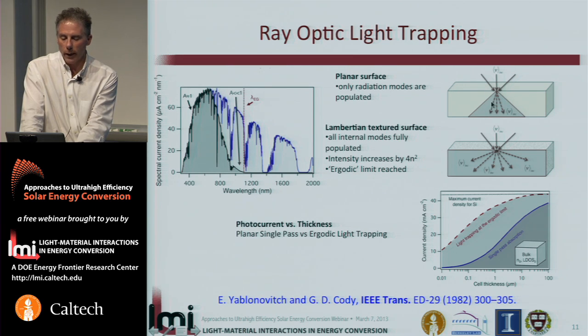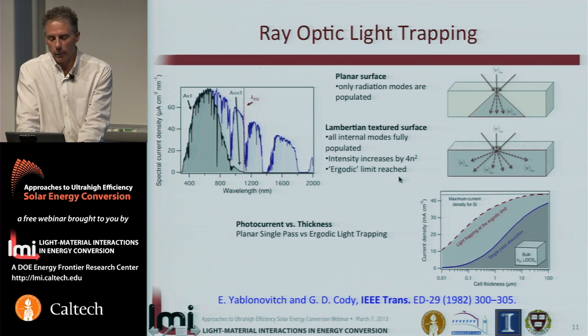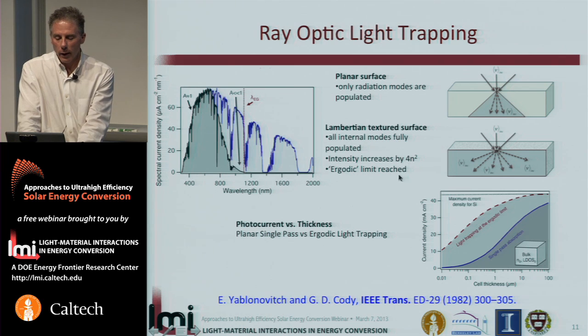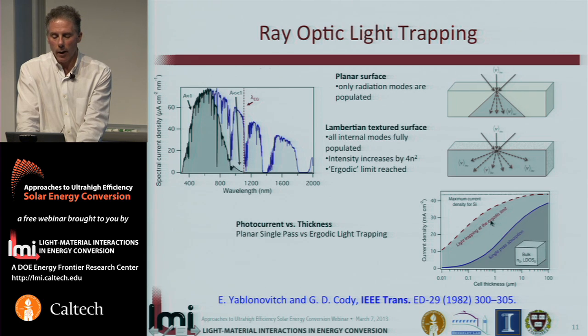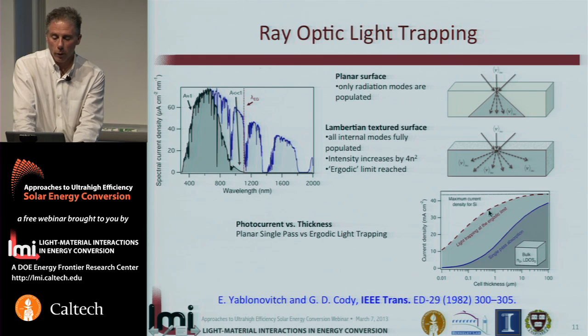radiating modes that lie within an internal absorption or, by reversal, emission cone. But by producing scattering structures on the surface, if we can now scatter light obliquely out of this internal absorption or emission cone, we can fully populate the modes, giving rise to an increase in the internal intensity by a factor of 4 times the refractive index squared. So for a fixed photovoltaic absorber thickness, one can think about increasing the photocurrent. Or, if one has a target photocurrent in mind for a solar cell, one could then design, in principle using light trapping techniques, a thinner solar cell to achieve the same target photocurrent.